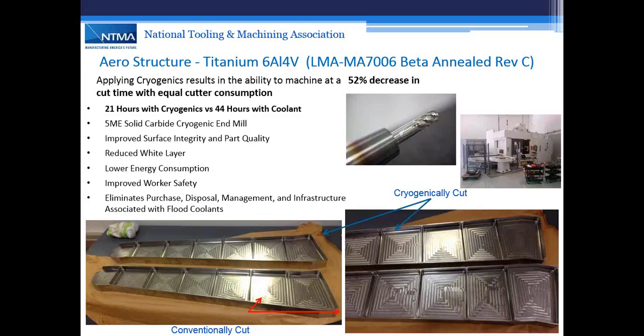This is that landmark study for us that I talked about earlier. We had Lockheed, a lead programmer, coming to our facility, used our 800 size horizontal milling machine, which is cryogenically enabled. What he was able to do is machine this part, which is approximately 1 meter long, 12 inches by 2 inches. There's 14 pockets, 7 per side. You use conventional titanium, 6-4 titanium cutting speeds. It was a 44-hour cycle time with wet processing.